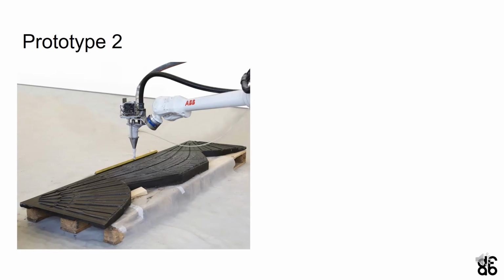The second one used 3 pieces of formwork treated with 3 different release agents to test removability. Furthermore, the accelerator was dosed in 2 different concentrations to get a very fluid concrete for the soffit and a more stiff filament for the ribs.